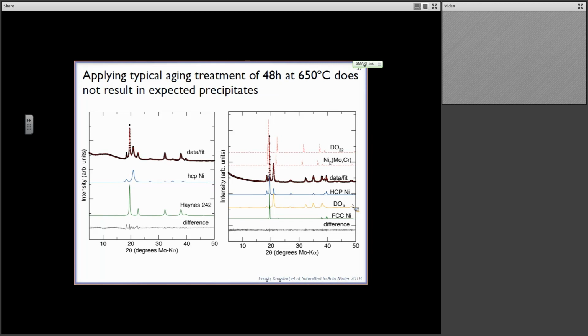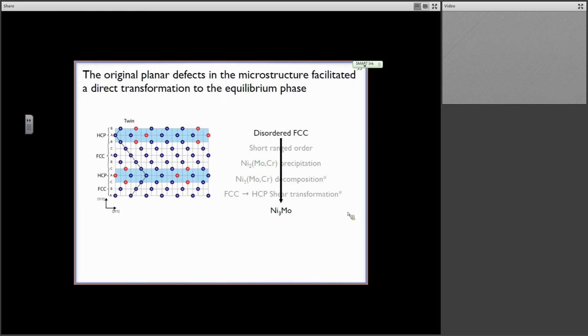And we had to corroborate this by a couple different means because it's actually not directly obvious from the TEM, but this DOA phase is rarely reported in the literature, largely because it takes so long to form, and because of this bit here, that even if you give it time, you still require some mechanical deformation to assist this shear transformation. But because we already have such a high density of HCP-like stacking in our microstructure, we've actually just skipped all of these steps, and we can study the implications of what this precipitate actually does to our microstructure by direct precipitation.